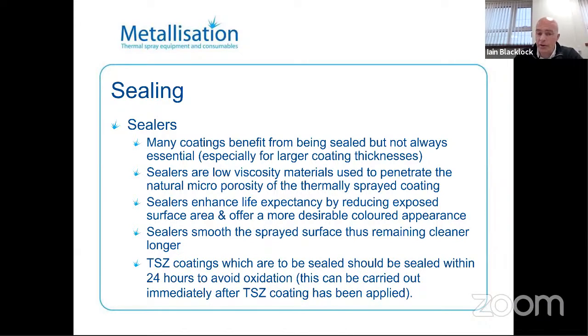For thermal spray zinc coatings which are going to be sealed, you should be sealing it within 24 hours of application of the thermal spray zinc, and this is to avoid oxidization. I think Michael discussed this as well with regards to the zinc oxide forming on the surface can create problems with sealing it correctly otherwise.